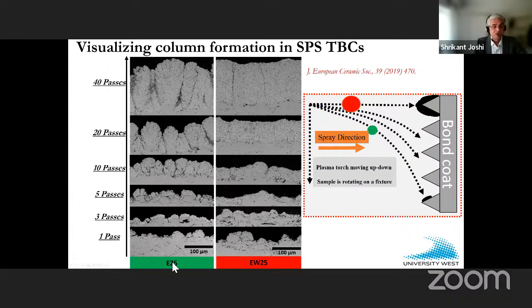coating formation. So as I was mentioning, if your target is getting a columnar structure, for most part, one would use ethanol, right? While use of water would give you a relatively dense coating, right? One advantage of trying to dig into this column formation mechanisms was also the fact that it allowed the thermal spray community to also get a hang of how to avoid columns, right? Which is necessary for many non-TBC applications. So that's something to remember for later.